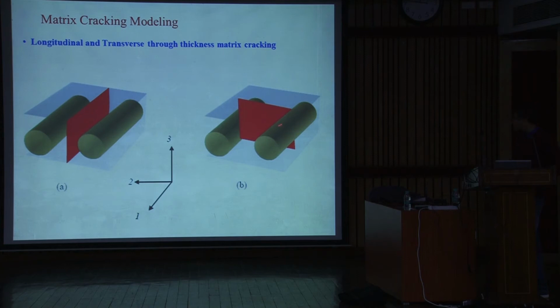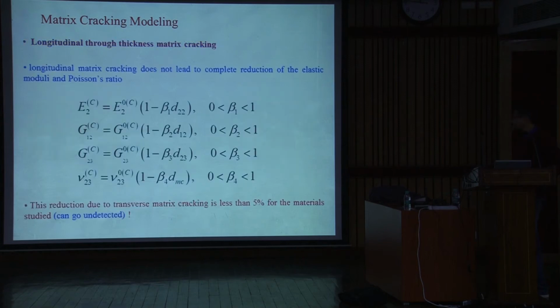But still this also happens, and its effect is less than 5% on the material degradation, and sometimes it goes undetected. So when you are characterizing, or doing the NDT or so, you should be very careful to quantify these numbers.